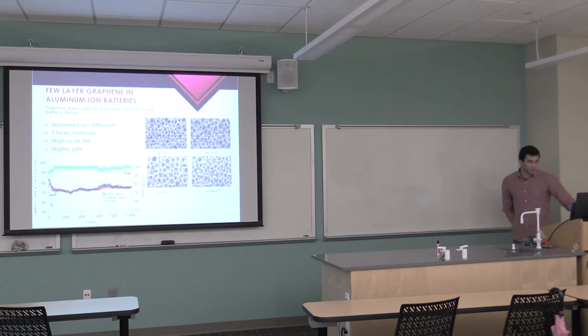But what I wanted to talk about here is that with the few layer graphene, again, it's a chemical vapor deposition process. And they found that using 4 to 5 layers of graphene saw the best diffusivity of ions into the electrode. And what that means is basically the ions can pass through and get all the way into the electrode and not be inhibited. So you got greater capacity and discharge current.